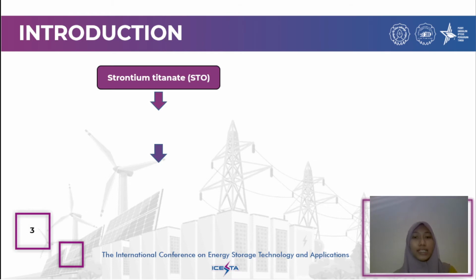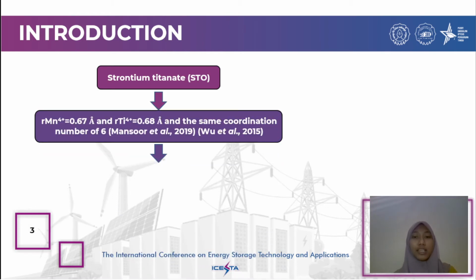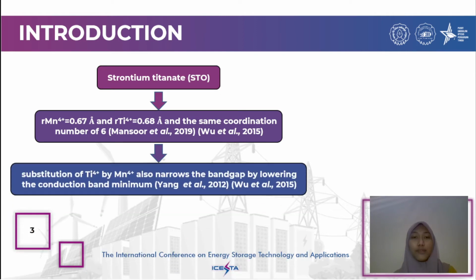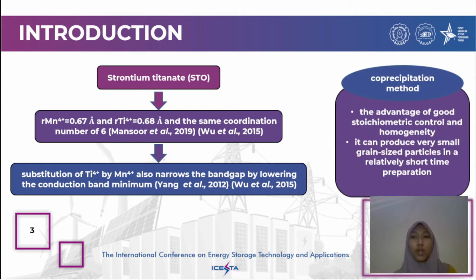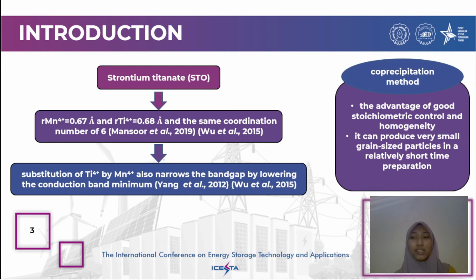Doping Mn is preferred due to its similar ionic radius with Ti4+ and the same coordination number. Substitution of Ti4+ by Mn4+ also narrows the band gap by lowering the conduction band minimum. First, the method used to synthesize SrTiO3. Among the available methods, the co-precipitation method has the advantage of good stoichiometry control and homogeneity. It can produce very small grain size particles in a relatively short preparation time.